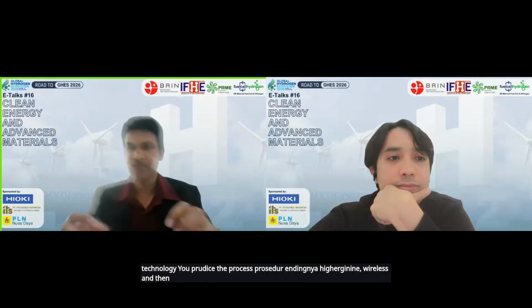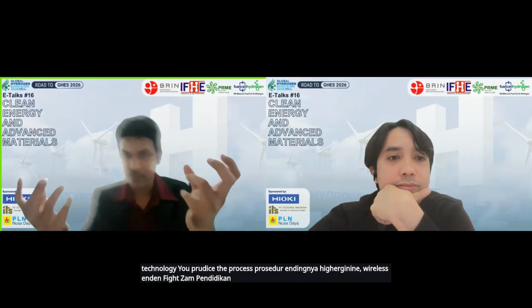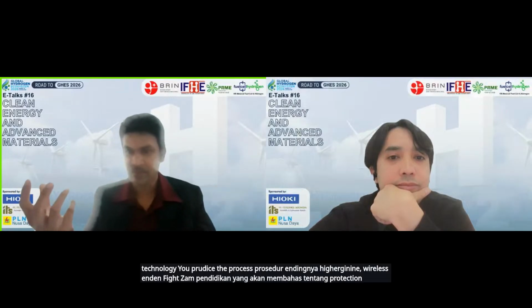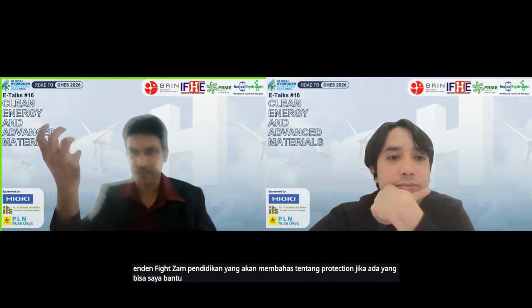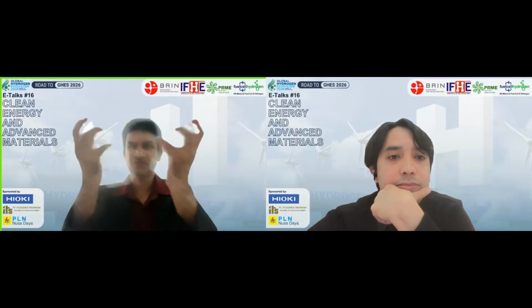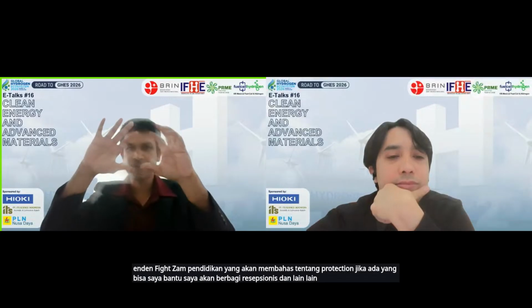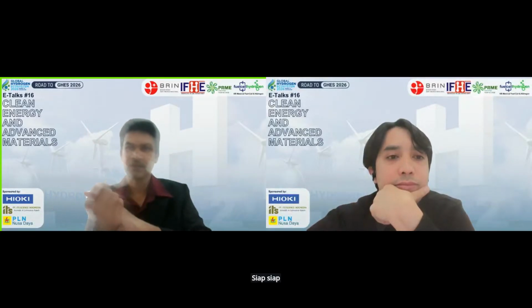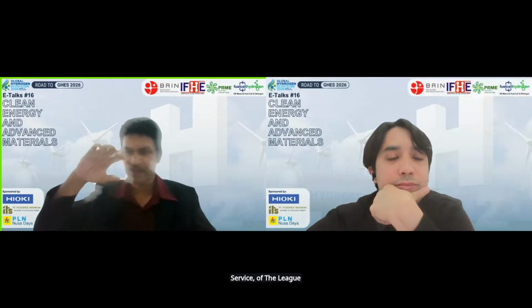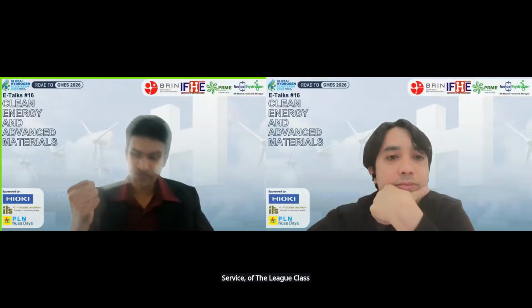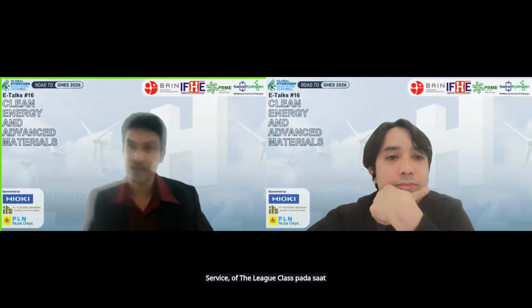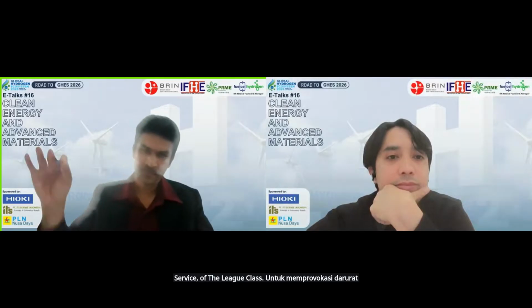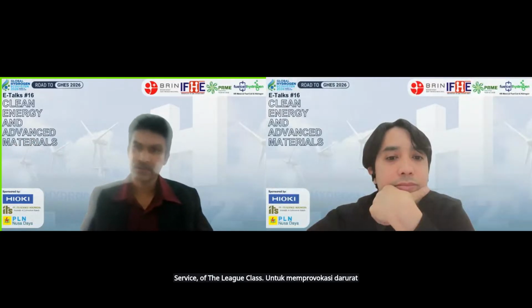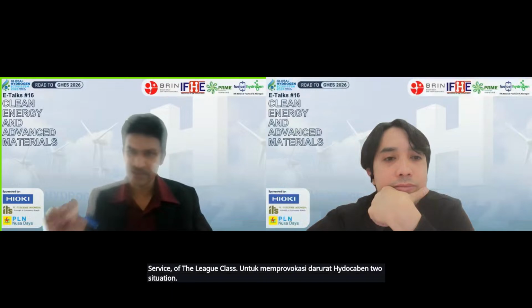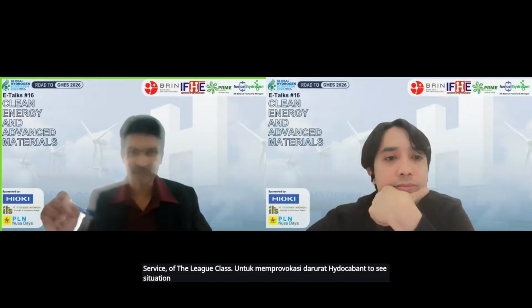And then, for example, the nickel will be exsolved from the perovskite structure. From the B site, we have A site and B site. From the B site, it will exsolve, and it will form a catalyst on the layer. It is something like modifying the surface of the electrode with exsolved nanoparticles to improve the overall performance of the electrode under the hydrocarbon fuel situation, which can reduce the carbon deposition, sulfur poisoning.